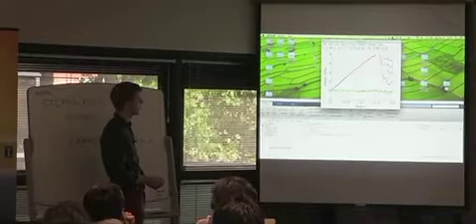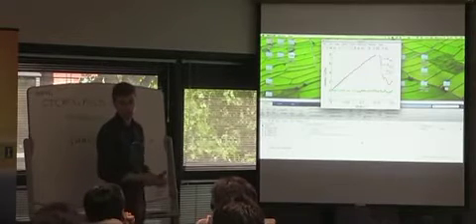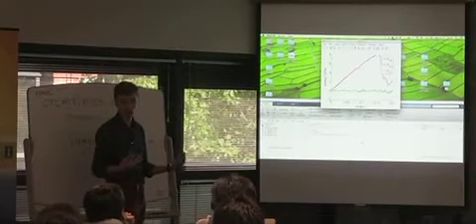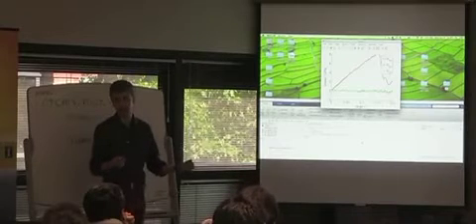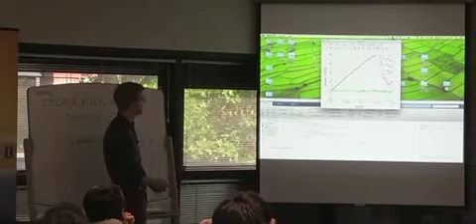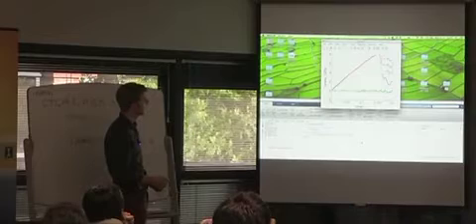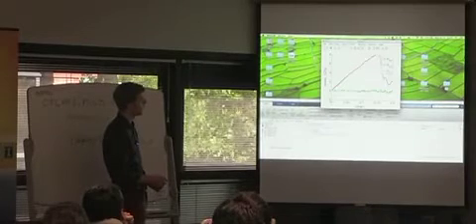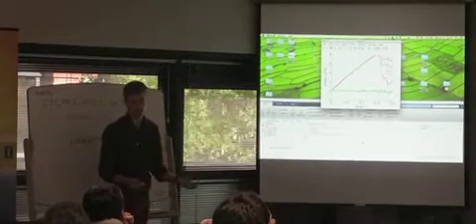The other thing to notice here is that, as we were watching the terminal output, we saw that as we hit a strain of 0.16, there was a precipitous drop in pressure, and this corresponds to the homogeneous nucleation of dislocations. We'll see that in OVITO: we moved elastically up to here, and then suddenly the crystal couldn't take it anymore and started to plastically deform. The visualization is going to show us that.